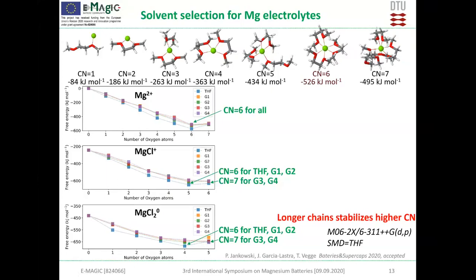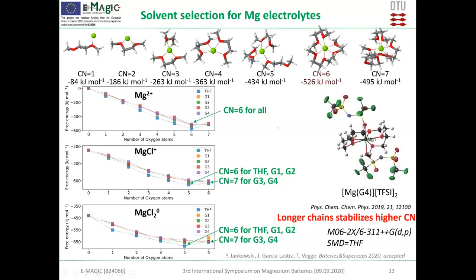That can be quite surprising, because for magnesium you would expect that it always will be coordination number 6 or maybe even lower. But indeed, when you look at the literature, there are already some reports about coordination number 7 for magnesium. This is for magnesium TFSI in tetraglyme, when magnesium is coordinated by the 5 oxygens from the tetraglyme and then 2 anions. And that's just because of the super strong chelating effect of these glymes.